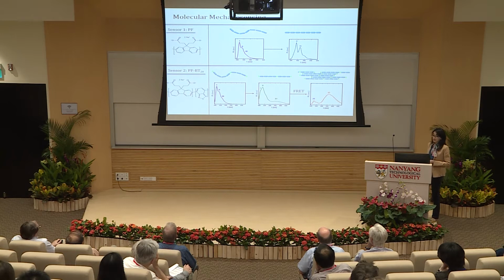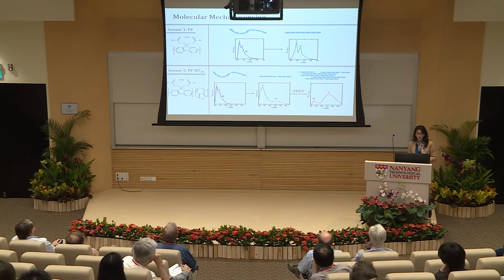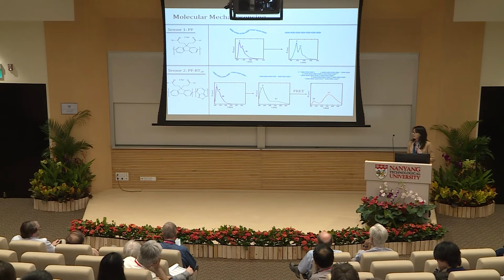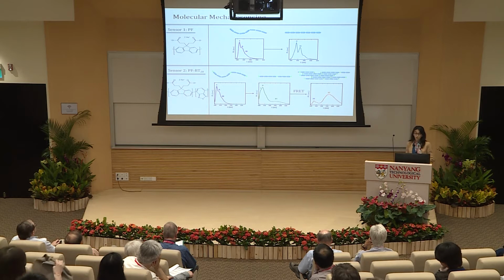This is a polyfluorene. Polyfluorenes are nothing new. They are blue light emitting sources, and in applications we already have a lot of them. But if you look at this structure, it is very aromatic, rigid and extremely hydrophobic. We want to do electrostatic complexation with these polyfluorenes, and it is not possible if they do not, of course, dissolve in aqueous conditions.